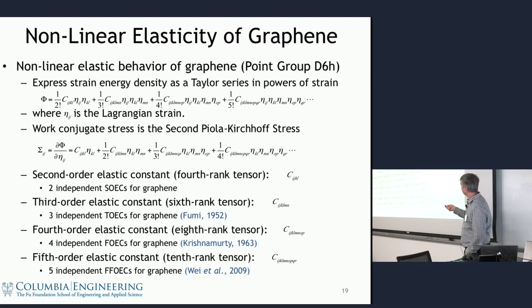This first term here is just your normal linear term, and it basically has in it your Young's modulus and your Poisson ratio. But then you get to higher and higher terms. So instead of just the quadratic term, they added 2 more terms here. And you can see these tensors start to get a little nasty. This is a nice 10th rank tensor. That gets a little fun. If you try to think about how many different terms are in this expansion and trying to fit all of those terms, I think it's around 1,300 total terms. You're probably not going to be able to fit 1,300 free parameters to any kind of experiment. If you did, we would usher you out of the building, never to return again.